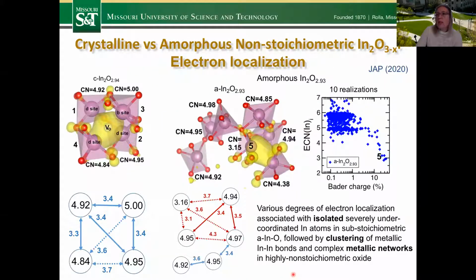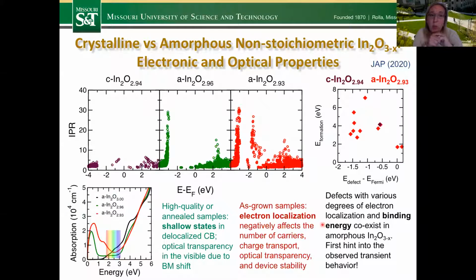Of course, as we start reducing the oxygen concentration, we start to have even lower coordination of indium, and localized states appear. So now we do see some similar patterns in terms of the structure, coordination, and distances to the oxygen vacancy. But the point is that these various degrees of electron localization associated with isolated, severely undercoordinated atoms may be followed by clustering of metallic indium-indium bonds, or even complex metallic networks when we go to very highly non-stoichiometric oxide. So again, the long-range structure really determines the localization and the electronic properties of these defects. And we need to look at the medium and long-range structure to describe the properties.